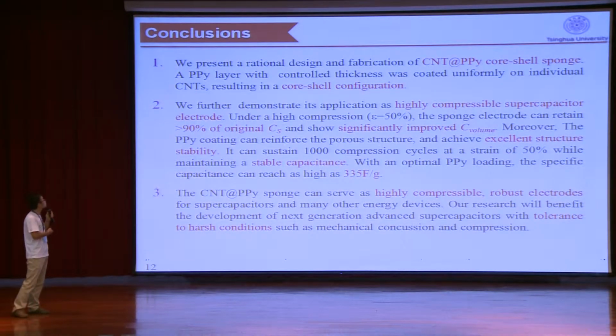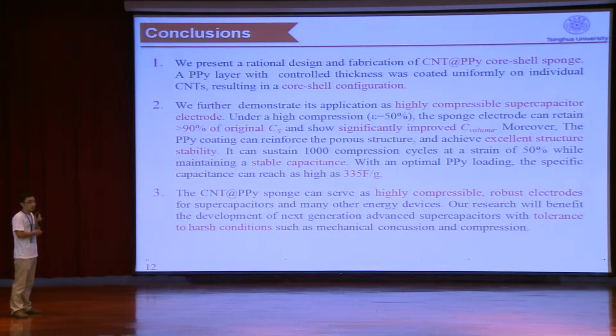And to conclude, first, we presented a rational design and fabrication of CNT and PPY core-shell sponge. A PPY layer with controlled thickness was coated uniformly on individual CNTs, resulting in a core-shell configuration. Second, we further demonstrated its application as a highly compressible supercapacitor electrode, and we obtained excellent performance. For example, it can retain more than 90% of original capacitance, and after 1,000 compression cycles, it can maintain a stable capacitance, and the maximum capacitance can be as high as 335 farad per gram. And third, the sponge can serve as highly compressible and robust electrodes for supercapacitors and many other energy devices. Our research will benefit the development of next generation advanced supercapacitors with tolerance to harsh conditions, such as mechanical concussion and compression.